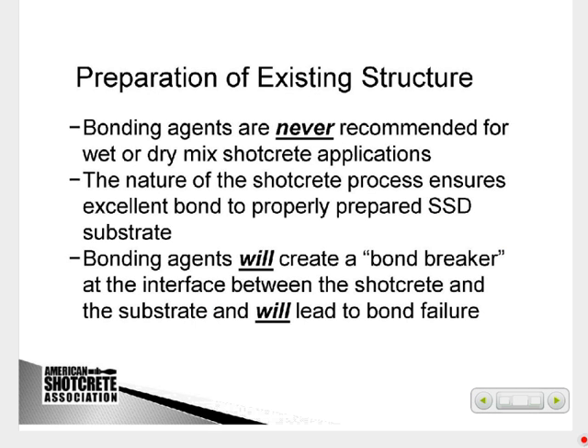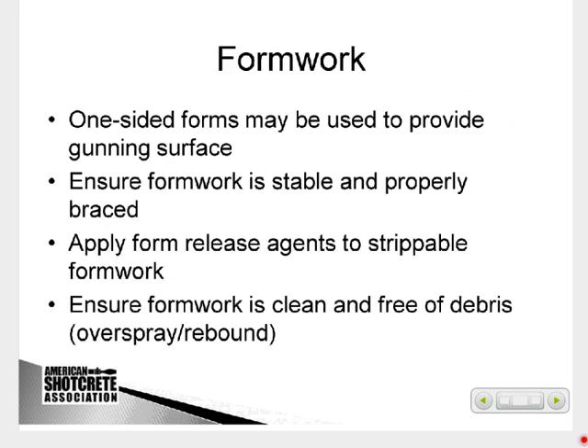We do not recommend bonding agents. If you're casting concrete against a concrete substrate, a bonding agent can be effective. With shotcrete, we actually have an abrasive, almost a sandblasting in place. The high velocity of the sand and cement and coarse aggregate actually kind of sandblasts the surface, opens it up, and encourages a very good bond of the fresh shotcrete paste to the concrete substrate. If you have a bonding agent, a lot of times it can actually tend to be sandblasted off by the shotcrete. And we've also run into problems where if you're not in the open window time of that bonding agent, it can act as a bond breaker rather than a bond enhancer.